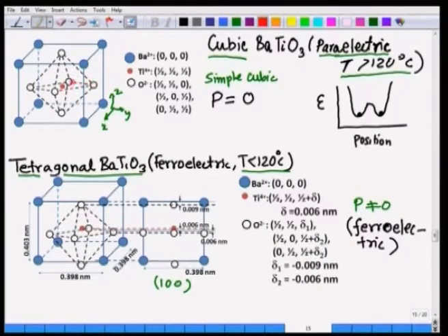Take these 4 oxygen atoms, and in order to make a tetragon, start squeezing these 4 atoms slightly inside, while extending these two oxygen atoms, pull this up and pull this atom down. Imagine stretching these two particular atoms farther apart, and as a consequence pulling these 4 oxygen atoms closer. If you do that, what is going to happen? You see, the titanium is nicely sitting in the center. If you want to squeeze these oxygen atoms in, then the only way out is that this titanium atom should pop out of the pocket. Either it can go up or it can go down.